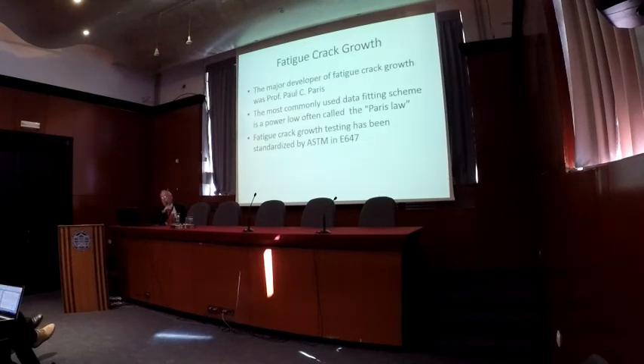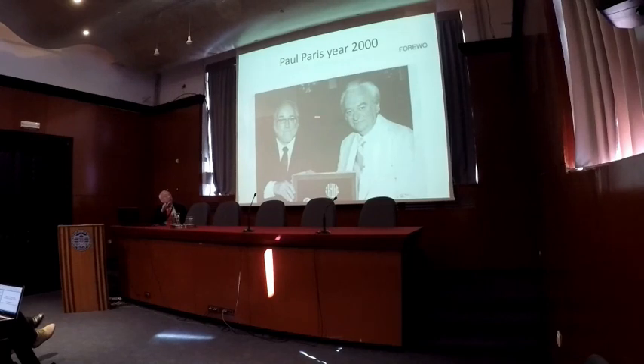And this is then a power law, and the fact that it worked was credited to Paul Paris. That law is often called the Paris law, and that has been standardized then, fatigue crack growth, by ASTM as well in a different standard number. But anyway, here's a picture of Paul Paris receiving an award, and this was in the year 2000, and he unfortunately passed away earlier this year. So many, many people said that they had seen him not too long ago, and they recognize him around the world now. Not only did he make a contribution in fatigue, but every aspect of fracture mechanics, from the linear elastic to the nonlinear, everything, he made a contribution.